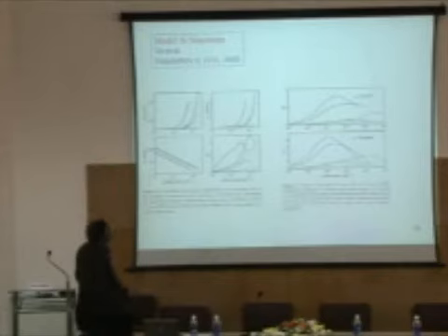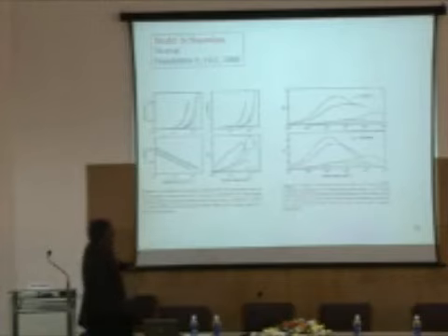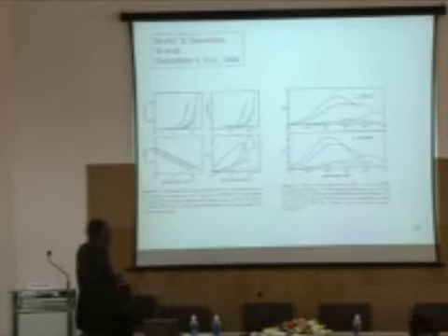So that's the idea. This is a calculation which was done for silicon nanowires. As a theorist, you can see theorists are much more optimistic. You can change the concentrations, you can change the size. We are now limited, unless we get next generation computers, to treating about 300 particles in ab initio calculations. But we need about 1,000 particles, which is sort of a next game. We can't handle them. But what we find is that depending on the thermal conductivity of the lattice, you can get large ZTs. But I believe there are other issues. These numbers are too high from theory, but we'll see how these numbers come down to relate to experiment.